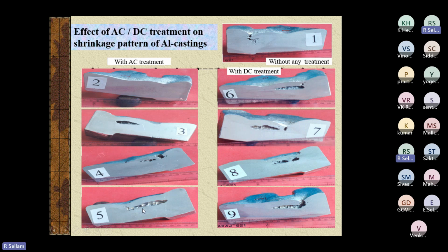Now there is some interesting phenomena over here. If you treat with AC, the internal shrinkage is showing, but the surface is more or less smooth. That indicates the entrapment of gas in that region. But here in DC, the internal surface is showing roughness. That means the roughness tips, that is the tips of dendrites, are there as gas is being removed. That is showing in this zone.